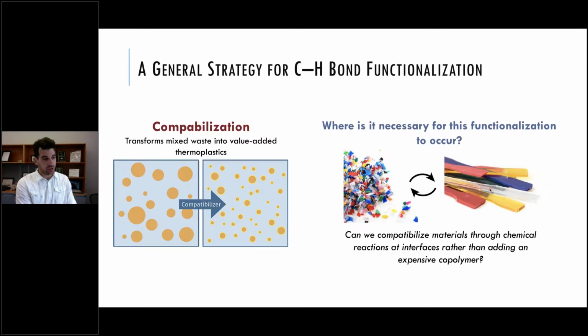Yeah, I mean, that will be a challenge moving forward for sure. I think the inherent advantage to our approach is we are using radical chemistry. A radical is the reactive intermediate that we're using. And the great thing about radicals is they work in the presence of water, right? Biology uses a lot of radical reactions. So while they are very reactive intermediates, they don't get quenched by water or other common things in the atmosphere, which is very good. They are sensitive to oxygen, but in an extruder there's not a whole lot of oxygen. There's not ways to transport oxygen. So we found, and this is pretty well known, that in an extruder, oxygen is at a pretty low loading, and these reactions can still work.